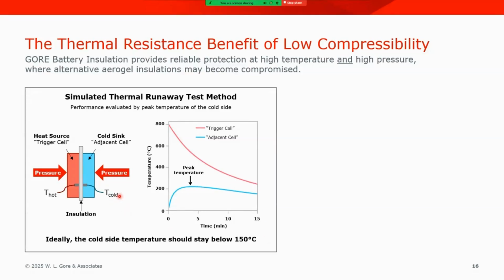Now, our test rig also has the ability to vary the amount of pressure that we're applying. So we can apply modest pressure of about 50 kilopascals, and we can discretely increase that pressure in subsequent experiments to see how the pressure affects the backside peak temperature. Keep in mind that ideally the cold side temperature should stay below about 150 C, because above 150 C is where changes begin happening to separator materials inside lithium-ion batteries, and that's where additional breakdowns can occur. So 150 C should be kind of the target in terms of keeping the cold side cold.